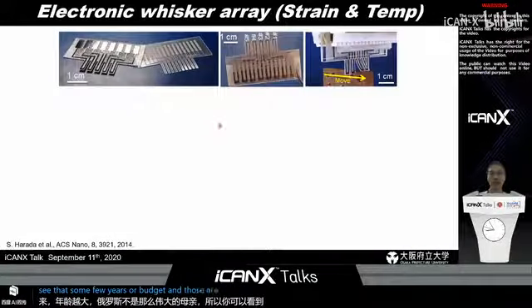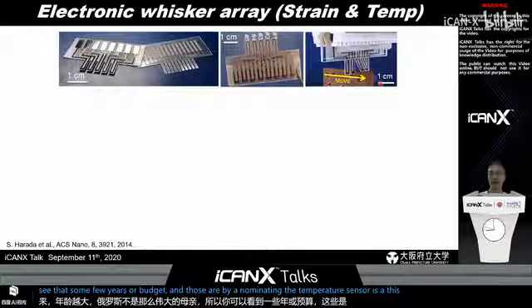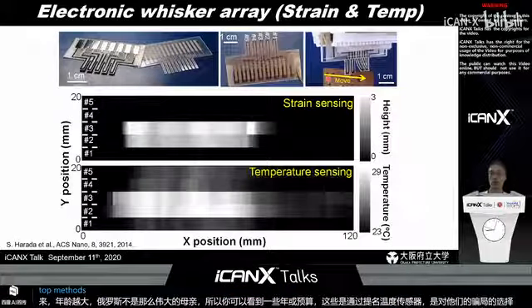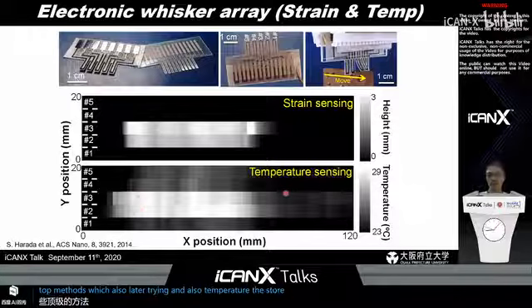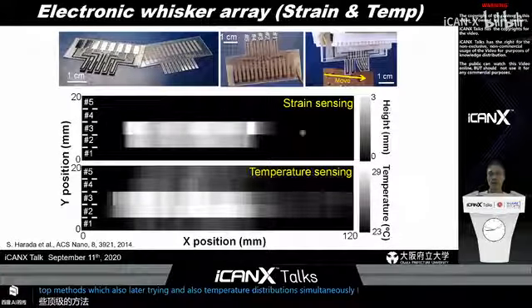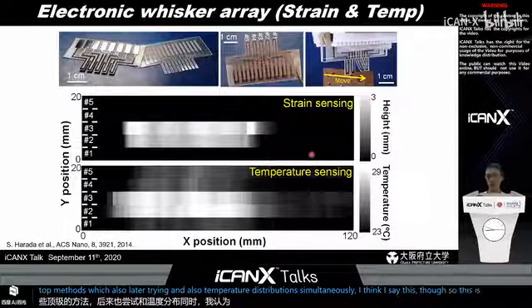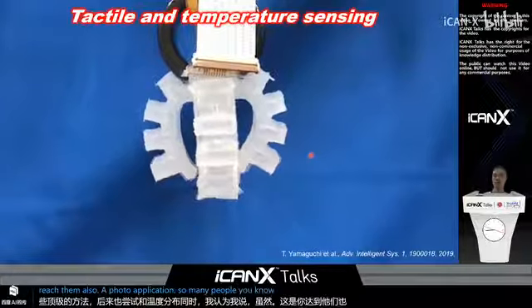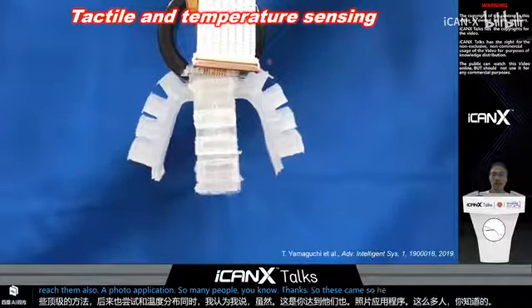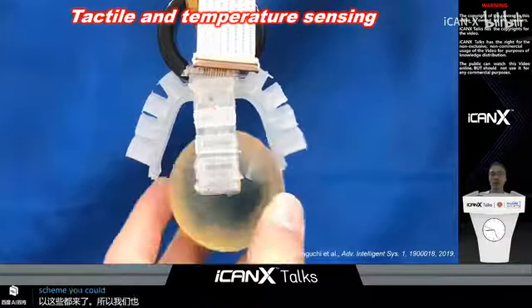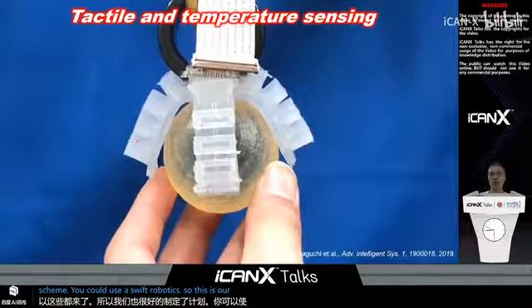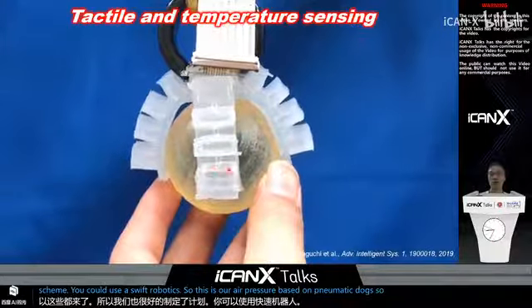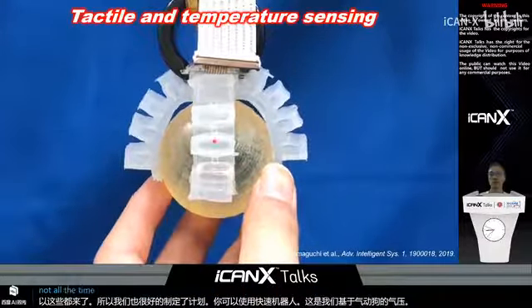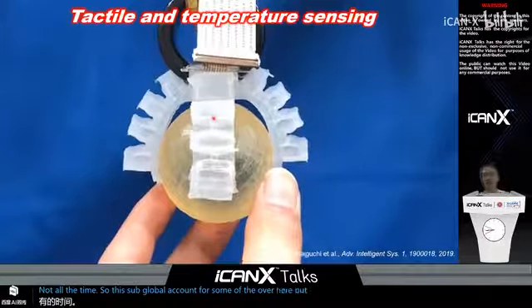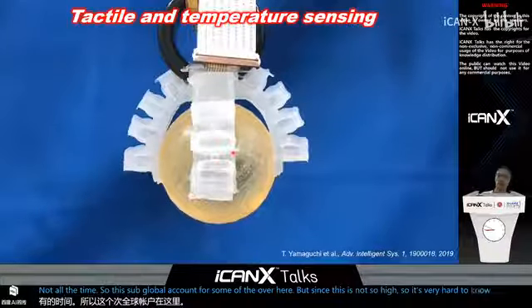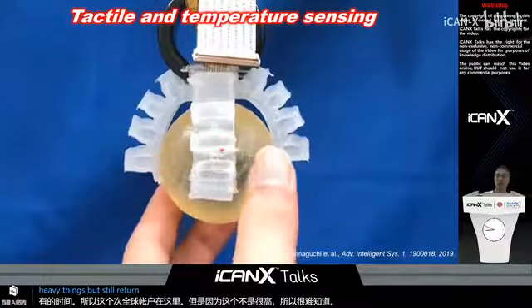And also by laminating a temperature sensor with this strain sensor, we scan a hot metal plate. So we can monitor the strain and the temperature distribution simultaneously, as you can see in this result. So this is the e-whisker for robotic applications. Many people think of e-skin. Here we also developed an e-skin integrated with soft robotics. This is an air-pressure-based pneumatic soft actuator to make a robot hand. This soft robot can hold objects, but since the air pressure is not so high, it is very hard to hold heavy things. But still we can hold a ball or some objects with this structure.